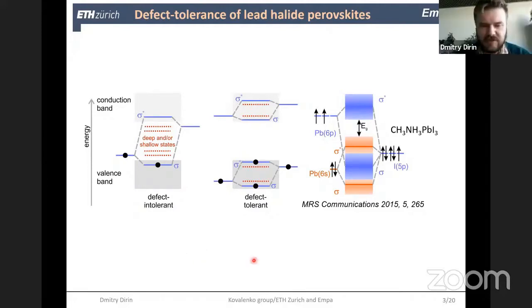I will try to quickly summarize what I wanted to discuss on this slide. So in conventional semiconductors, the top of the valence band and the bottom of the conduction band are formed by bonding and antibonding orbitals, correspondingly. And this means that dangling bonds and vacancies in conventional semiconductors will create deep or shallow traps. And as we usually always have some dangling bonds on the surface, this material cannot exhibit bright photoluminescence because of these trap states.